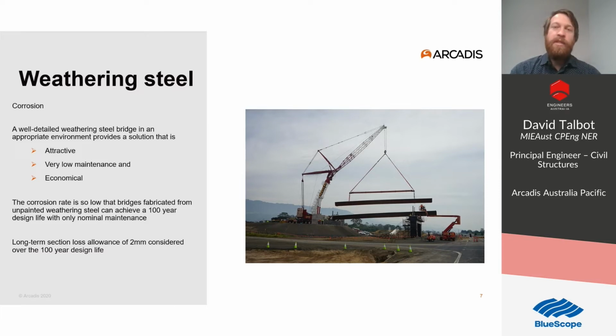For these 2 bridges on the Berry to Bomaderry project, a 2mm loss of section was considered over the 100-year design life of the bridge. And that 2mm is a fairly conservative number. Once the patina forms correctly, the long-term corrosion rate is very small. And typically it takes about 8 years for the patina to form completely.